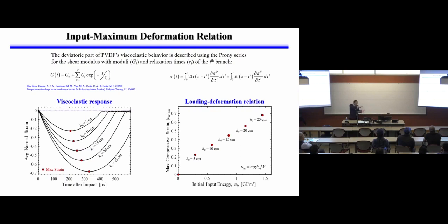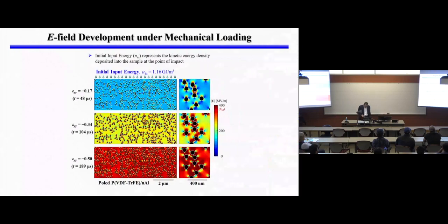Because it's a viscoelastic material, we have to consider that the loading stops and the material bounces back. And so that simulation allows us to capture, for each load intensity, for a given amount of energy input, what is the maximum strain we can achieve? We did that. This is a standard viscoelastic calculation that we carry out. And then here is what happens. You have the different strain components at different times. As we deform, we can see that the electric E field intensifies. I think this is a poled material, so this has piezoelectricity as well.